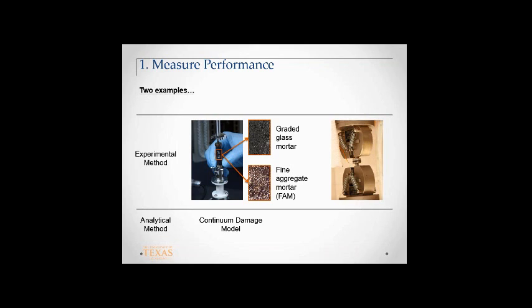Nowadays we are using a lot of recycled materials, and we are proposing to add rejuvenators, which can soften the oxidized binder. My question is, is there a proper way to mix that rejuvenator or additive into the binder? Because we generally add the rejuvenator on site in the mixture. It's not mixed with the binder, whereas here we are doing it with the binder. I think it's different from the mixture-level work. At the end of the day, when we are doing practical work, like hot in-place recycling, we are directly putting a rejuvenator on top of the mixture. Then how will we compare if we need to study the effect? There are two things that can happen in a real scenario.